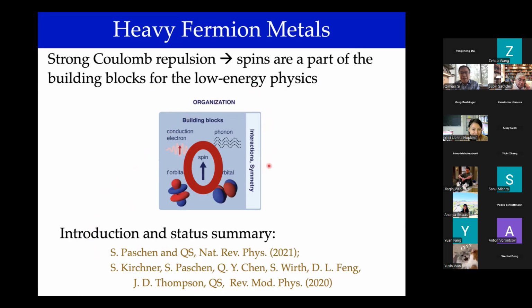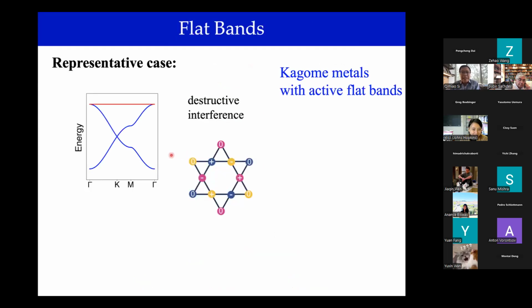One is heavy fermion rare earth or actinide based materials, for example, in which the interactions are certainly larger than the kinetic energy of the F electrons alone. They could be smaller than the kinetic energy of the spd electrons. So the F electrons act at low energies as spins, and they are part of the building blocks for low energy physics. In a way, one could also say that the F electron band being narrow by itself represents an atomic form of flat bands. And the second context that has been studied in more recent years in this context of flat bands, beyond the prominent case of moiré systems,